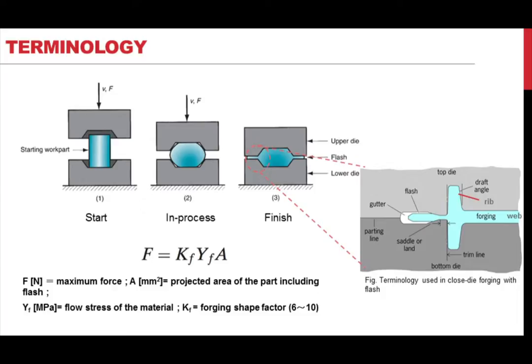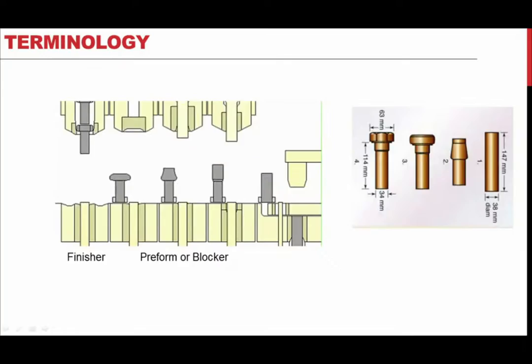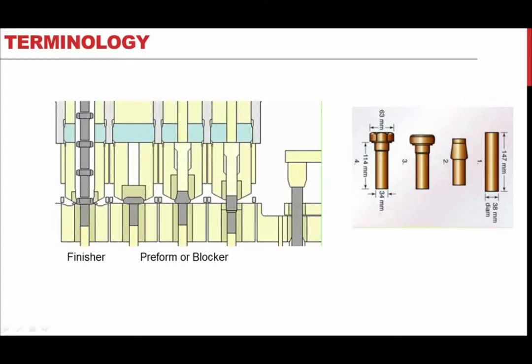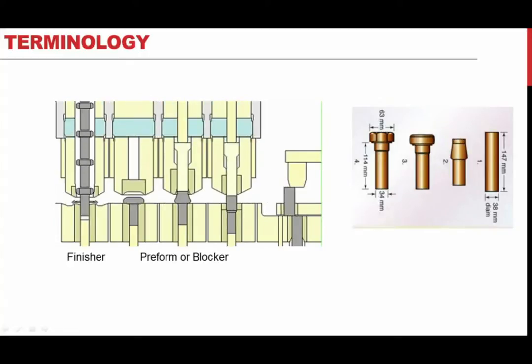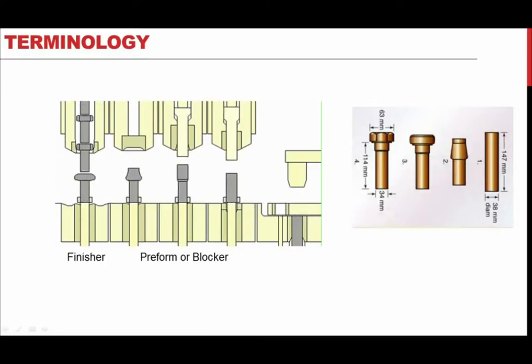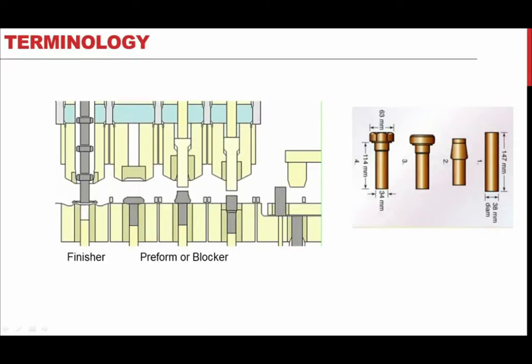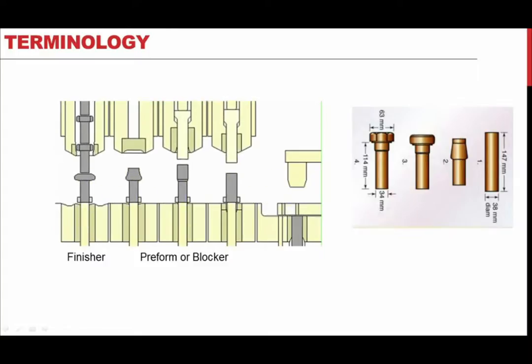The maximum force applied to the upper die is determined by three factors: the projected area of the part including flash, the flow stress of the material YF, which in hot forging equals the yield strength of the material, and a forging shape factor KF, which can vary from 6 to 10 depending on the complexity of the part's shape. For most parts, several forming steps are required in closed die forging to transform the starting blank material into the desired geometry. Several cavities in the die are needed for each step.